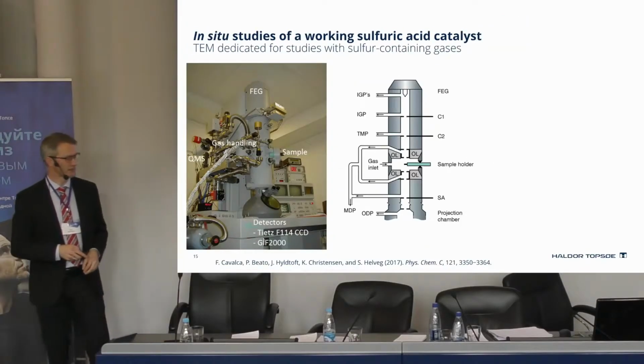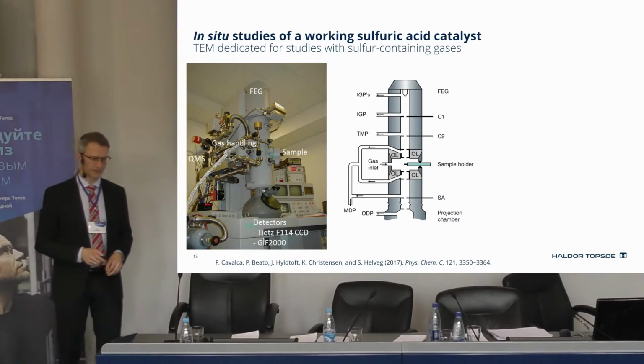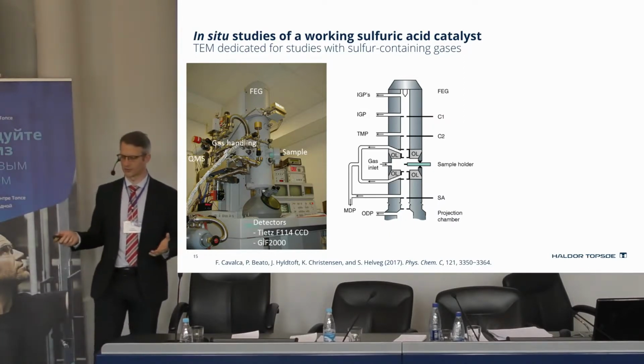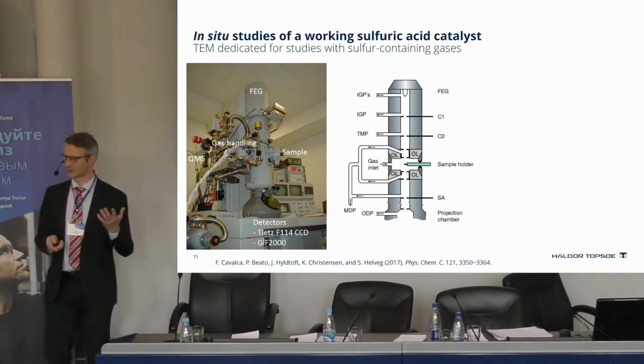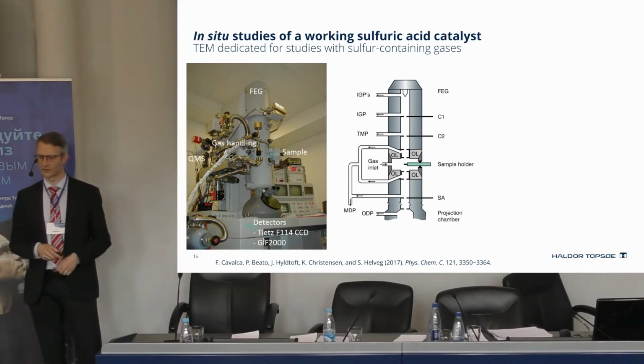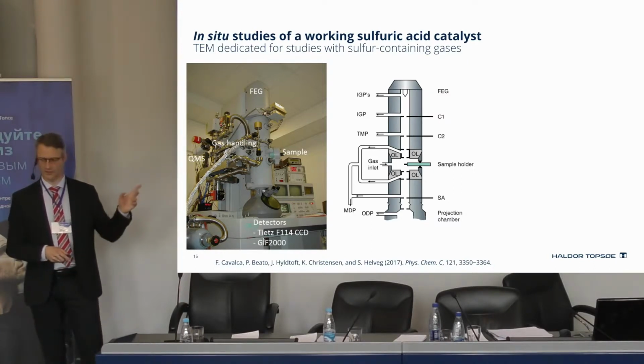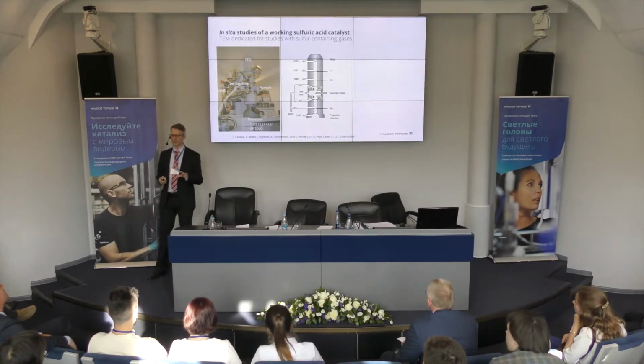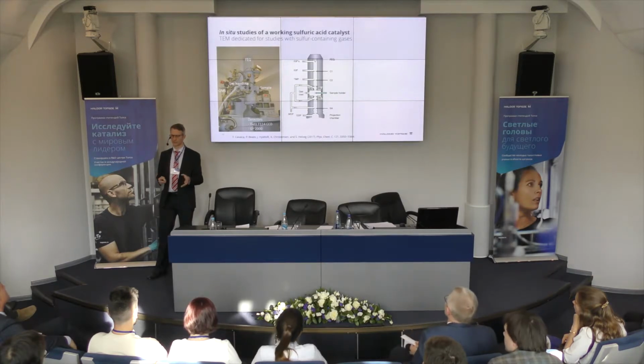And this has been quite a challenge because normally nobody wants to put sulfur in their microscopes because it will corrode the microscopes, and it's expensive equipment and it will also interfere with other experiments. So we decided in Topsoe to dedicate a microscope for these sulfur-related studies. You can say we decided to sacrifice it because now it's only for sulfur-related studies. It's special in the way also that we can operate with some millibar pressure of gas. A normal TEM operates maybe at 10 to the minus 9th atmosphere pressure, but here we can operate at say 10 millibar gas pressure, which is quite close to industrial conditions.